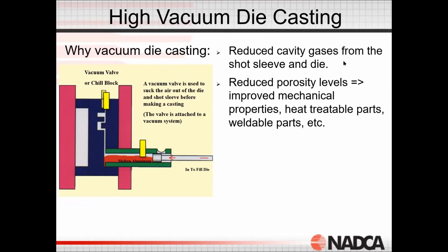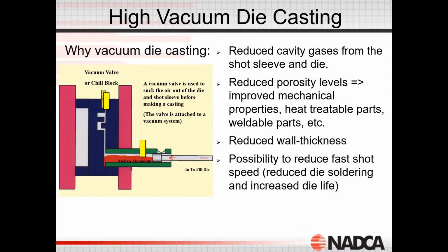We want to reduce the gases in the shot sleeve. We want to reduce the gases in the cavity and thus reduce porosity levels, improving those mechanical properties, making them heat treatable. We want to have castings with uniform and very small wall thicknesses, meaning 3 to 5 millimeter walls. So we can get the same type of strength, durability, and elongation out of a casting that's got a 5 millimeter wall as it does with a 10 and a 12 millimeter wall.